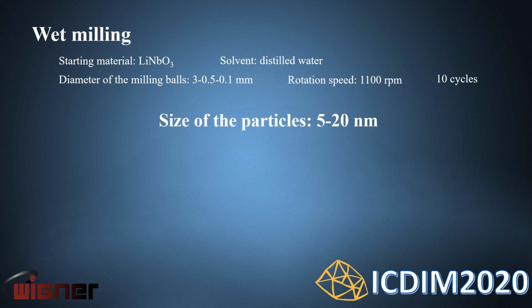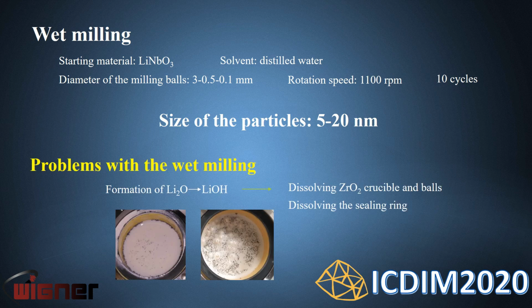At the end of this process, the size of the particles we reached was between 5 and 20 nanometers, which is very good for the application. But there was a problem.